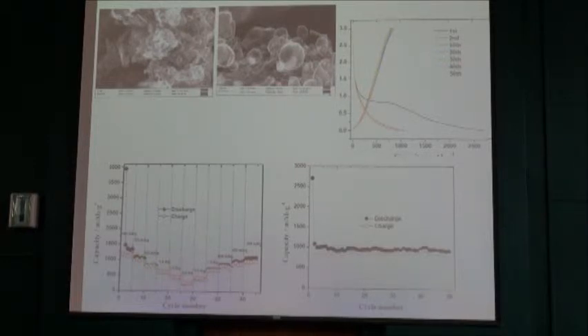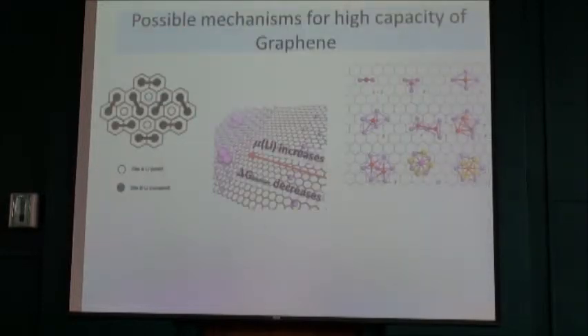They have a mechanism for why it is like this. Typically, like I said, you have a lithium atom for every other hexagon, right? Remember, previously we drew these hexagons. So every other hexagon has a lithium ion. But when you have these graphene spheres, you can actually have lithium clusters. In addition to every other hexagon, you can have a lithium cluster. This one has a 2 lithium atom cluster. So that will increase your capacity, right?